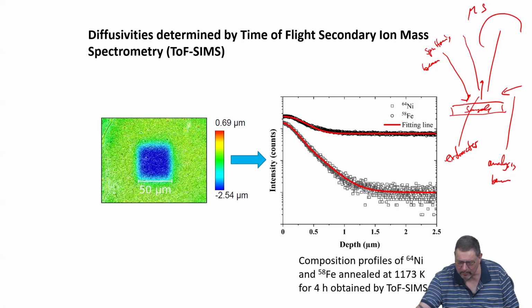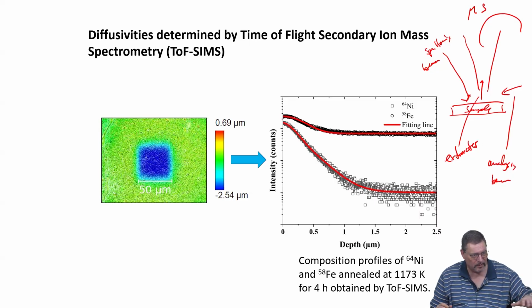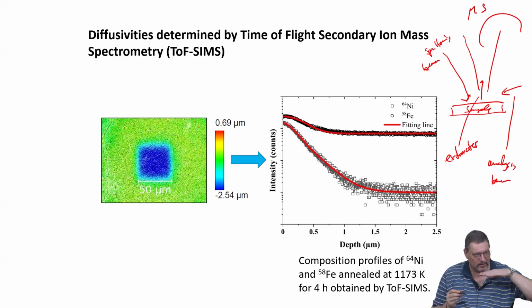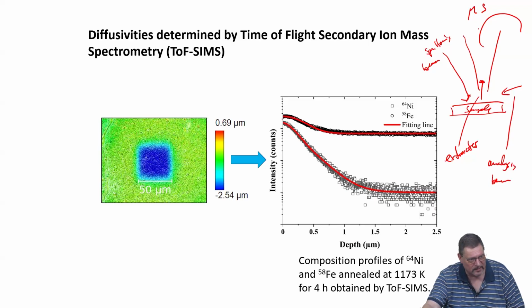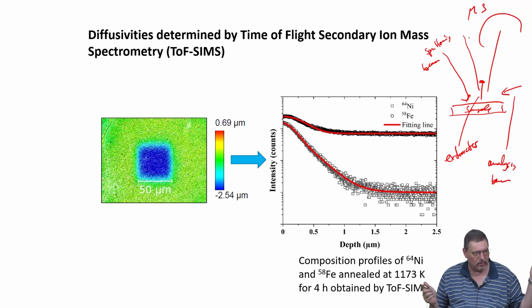So with this sputtering beam, you dig into the depth of your sample. And with this analysis beam, you kind of nicely slice off just the top surface in your sputter crater, and these then go into your analysis column. So you separate out the digging from the analysis, because the digging will create much more energy input in your material. So you basically sputter off, but you don't collect that information. And then you stop, and then you just sputter off gently. This goes into the analysis column, gives you the intensity profile, and then you stop again. You can dig deeper, and so on.